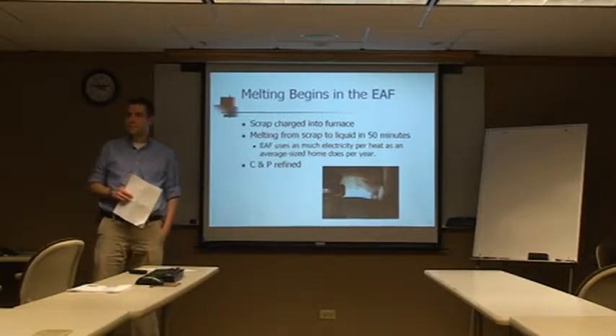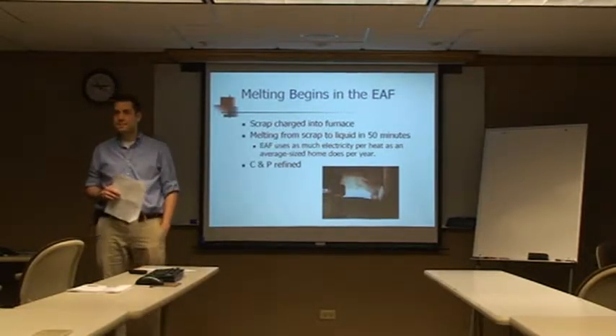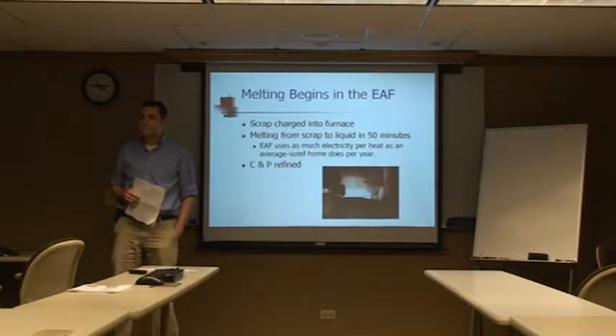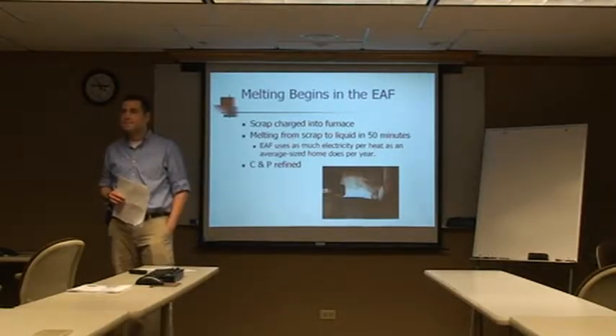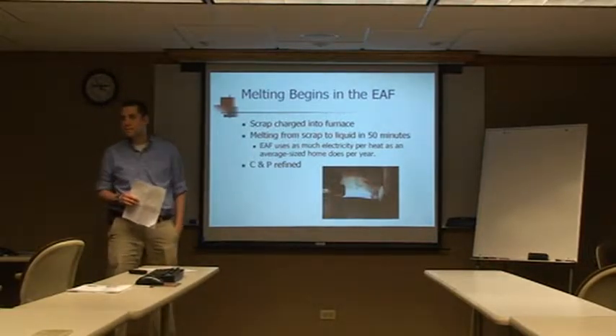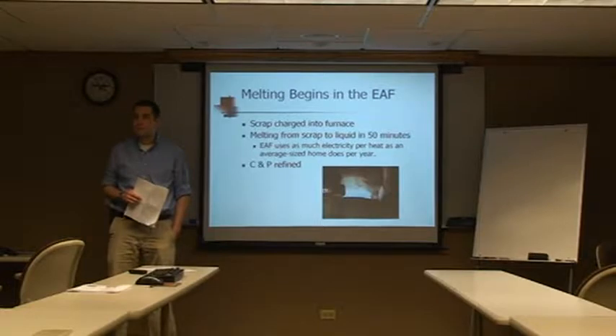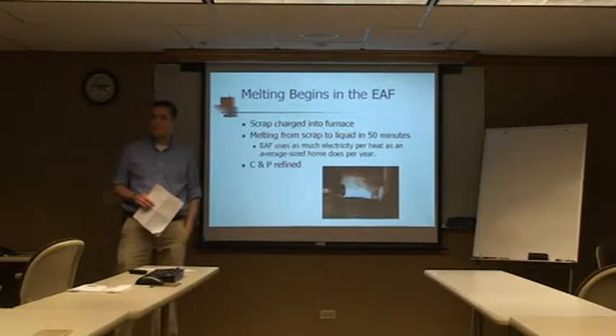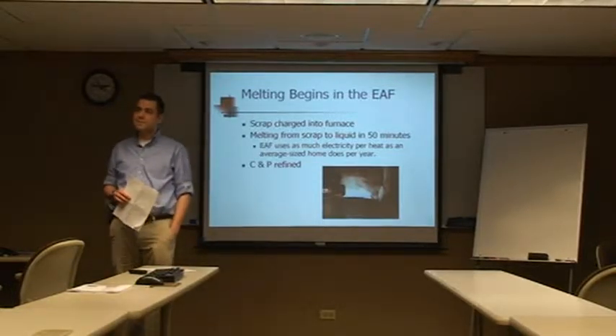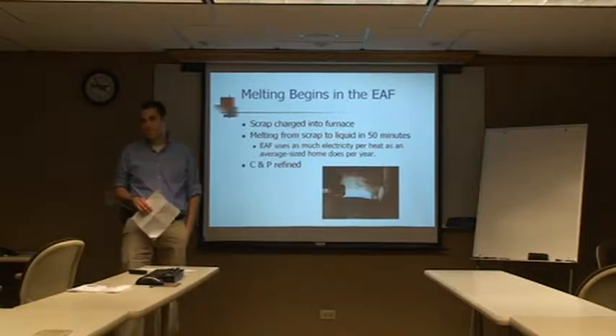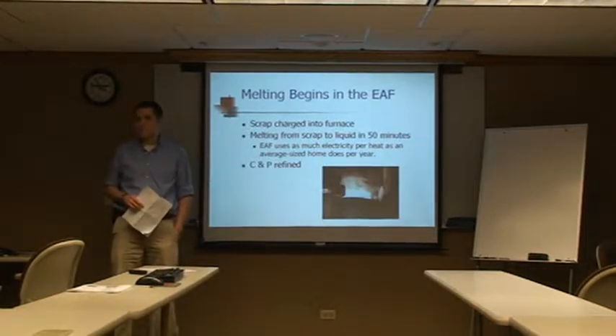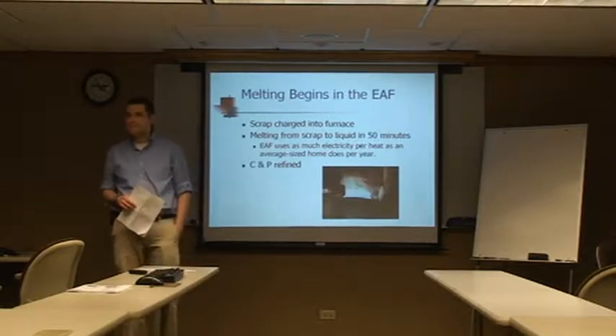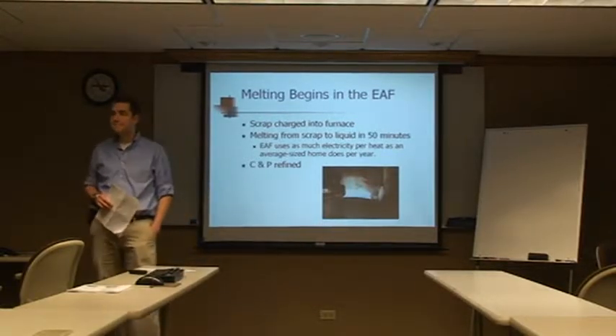When we first started the shop, it was 90 minutes tap to tap time. Since then, we've continued to improve. When we implemented that oxygen lance system, the first year was 86 minutes. It took us from there to about an hour, so we got 15 to 20 minutes out of our tap to tap time, which is 25%. So not only are we using electricity, but we're also using oxygen and chemical heating for that efficiency. And that's just one heat. That's a 45 or 50 minute heat, not even a full day's production.